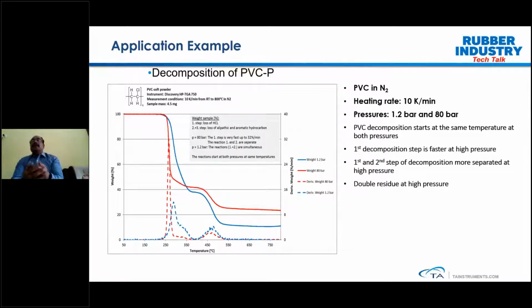And you can see clearly the two step changes of a PVC. One is first it will be evolving the HCl from the things. And then the second decomposition corresponds to the loss of aliphatic and aromatic hydrocarbons.